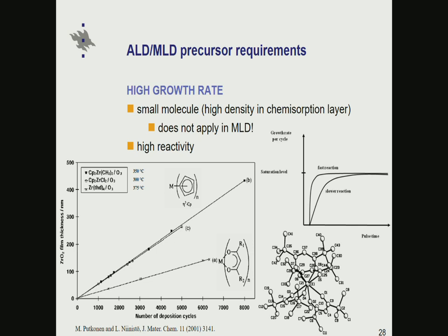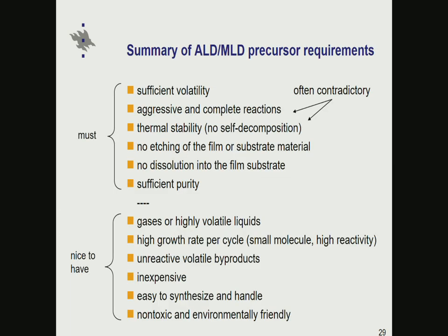And typically it also means that these smaller metal compounds show higher reactivity. But this is the point where MLD becomes different from ALD, because in MLD essentially all the atoms in the precursor molecule are also left in the film. As a result, in MLD, if you have a large molecule and can still make it volatile, quite often it translates to higher deposition rates as well, provided that there are no reactions from both ends of the molecule, as Ulla was also mentioning.